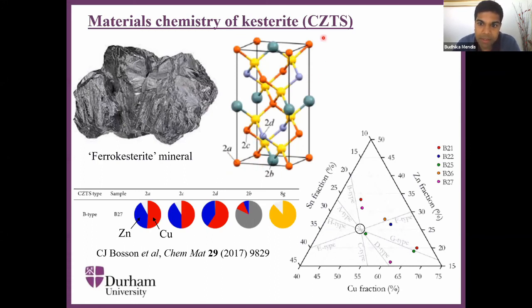What you find in kesterite is that if you deviate away from perfect stoichiometric composition, then you could have various atoms sitting in individual sites within the crystal lattice. So for example, if we take this corner atom labeled 2A, in the ideal structure, this should be a pure copper atom. But what my colleague Douglas Halliday found was that if you move slightly away from this perfect stoichiometry, then instead of having perfect copper occupancy, you could also have intermixing with zinc.